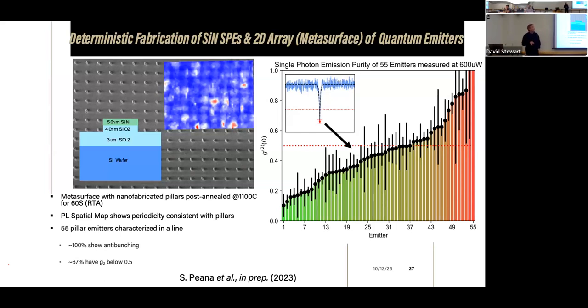And here I'm showing again the distribution of this G2 as a number of emitters. We checked 55 emitters in a row, one after another, and you could see that 67% of them actually have G2 below 0.5, indicating they're single photon emitters. And another important thing, they're all anti-bunched. 100% of them show G2 less than 1. So they clearly have good quantum properties.